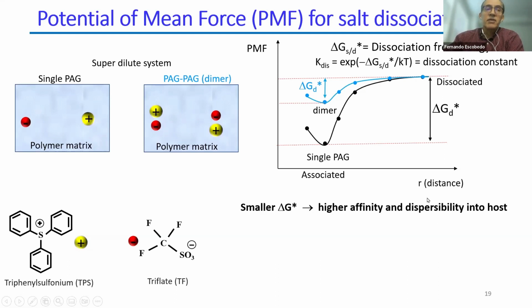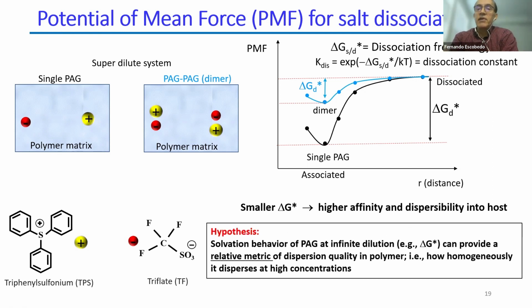Because in some ways, this corresponds to the penalty, the work that's needed to separate these two moieties. Our main hypothesis for our methodology was that the solvation behavior of PAGs at infinite dilution, which is this calculation, can provide a relative metric of the dispersion quality in a given polymer, so how homogeneously it disperses at high concentrations. Because in real life, they don't use these things at such dilute concentrations, but at relatively high concentrations.